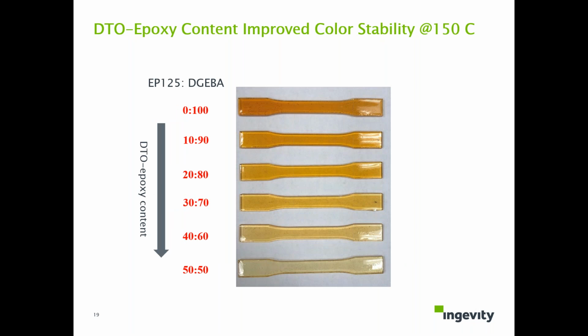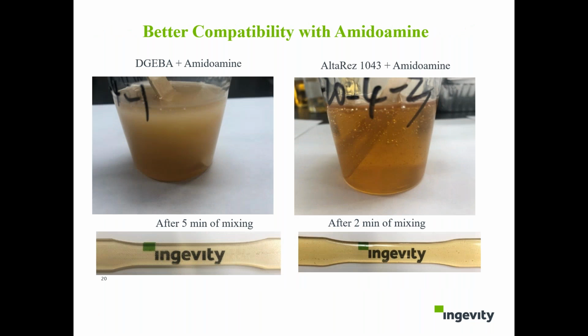And the same question: how much percent DTO-epoxy in the formulation can improve the color stability at high temperature? We started with 0% DTO-epoxy up to 50%. So you can see that as the DTO-epoxy percentage increases, the color stability at high temperature improves significantly. So we continue working on this DTO-epoxy with different hardeners in the market.